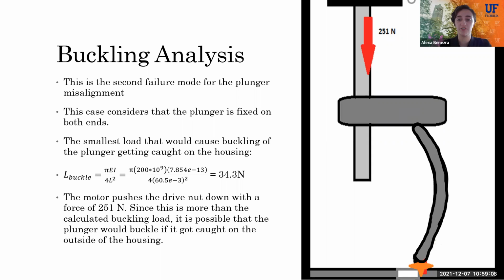Since the motor pushes the drive nut down with a maximum force of 251 newtons, this is more than the force to buckle the 3/16 stainless steel. It's worth noting that this is an unlikely failure mode because the housing would likely break before the steel plunger would break due to its lower tensile strength.